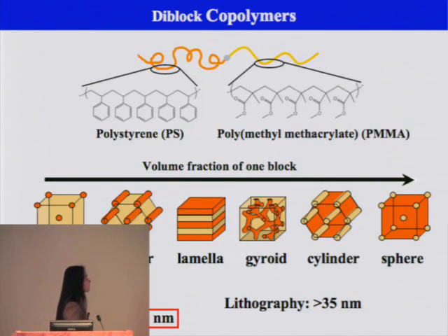But here, you can easily tailor the dimension of individual structures by tailoring the size, the dimension of your polymer chain. It easily gets itself into the 10 to 100 nanometer range, and that is really the sweet spot. Just for reference, if you look at my hair, the diameter of my hair is about 40 micrometers, so that's about 3 orders of magnitude bigger than what we're talking about here.